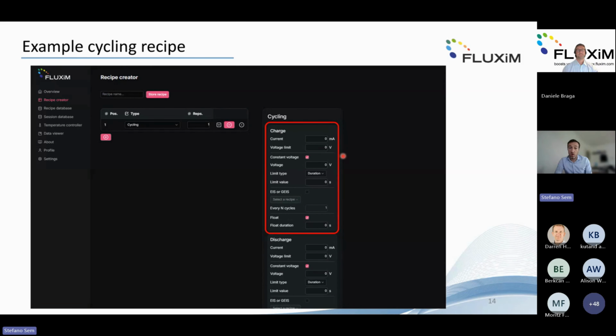If he wants an additional constant voltage step with a certain duration, here a limit can also be added. Instead of the duration, a certain current limit can be added, so until the current reaches a certain threshold, this voltage step is finished. One can also add an impedance, EIS or GEIS step at this point. Can also say if the impedance needs to be done every cycle or every whatever number of cycles.